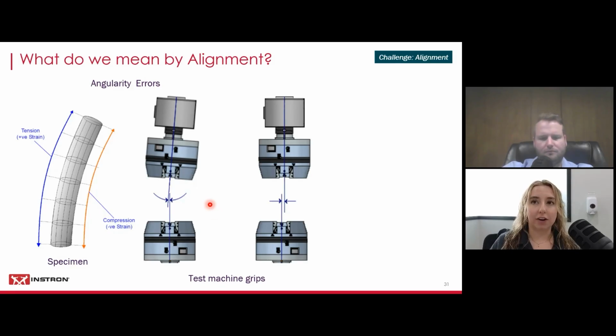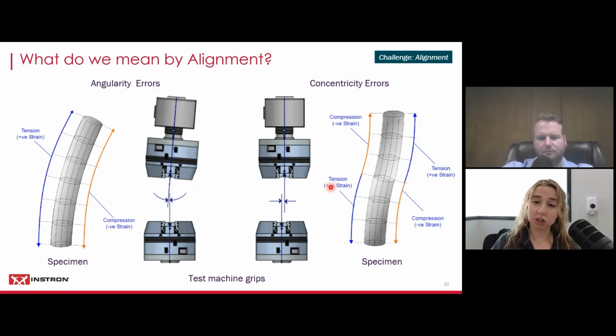The next kind of error that we typically see is concentricity. So our grips may be parallel, but they are offset. So what this is going to do is create a worse kind of bending error or bending moment that creates this S-type bending. So now we actually have regions of positive and negative strain occurring in the specimen. And if our specimens are shorter, then we're going to see an even increased effect of the bending moment on those specimens rather than if they were longer within that load string.